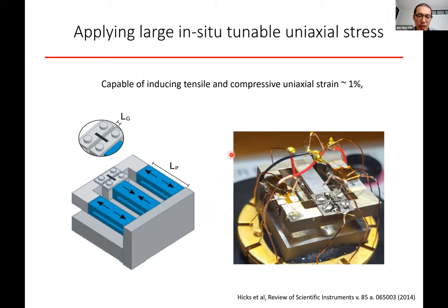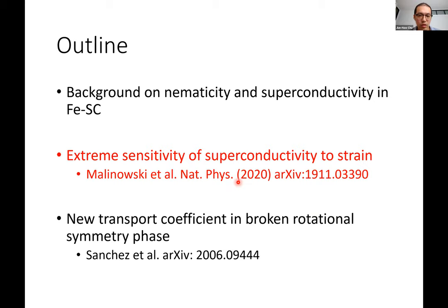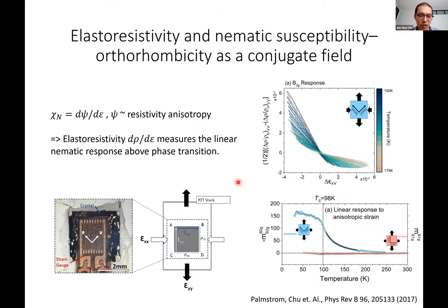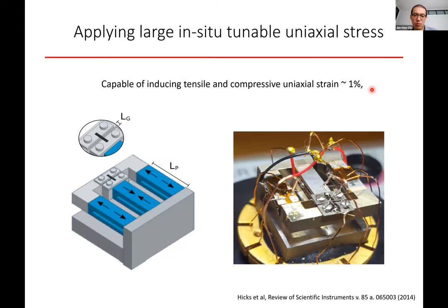Now, I think the advantage of this method is that you can apply both tensile strain and compressive strain, so basically both positive and negative pressure in the same device. This will turn out to be useful in determining the nature of the observations we made. Obviously you can also apply tensile and compressive strain using the elastoresistivity technique I mentioned a few slides before, by gluing a crystal on a piezo stack. But just due to the nature of piezoelectric materials, the strain you can apply is definitely smaller than 0.1%, and at low temperature it could be even lower.